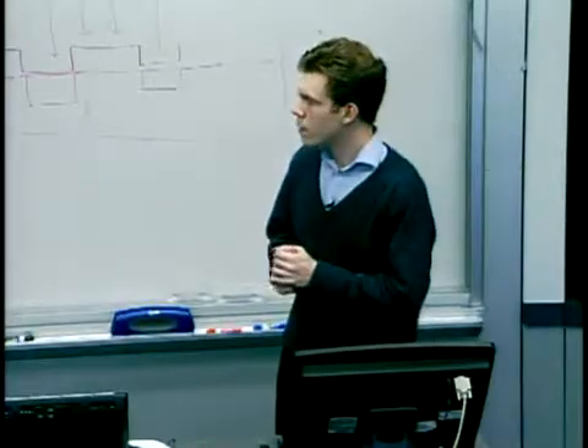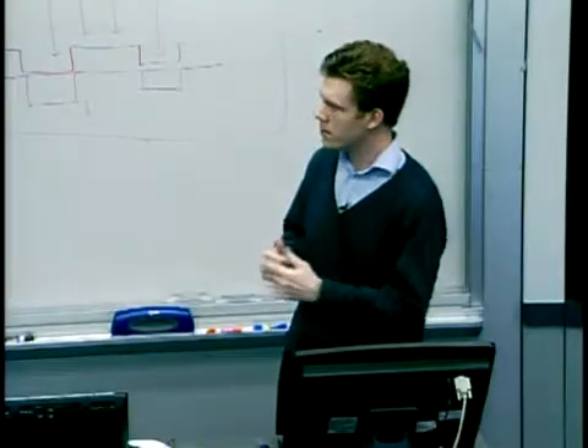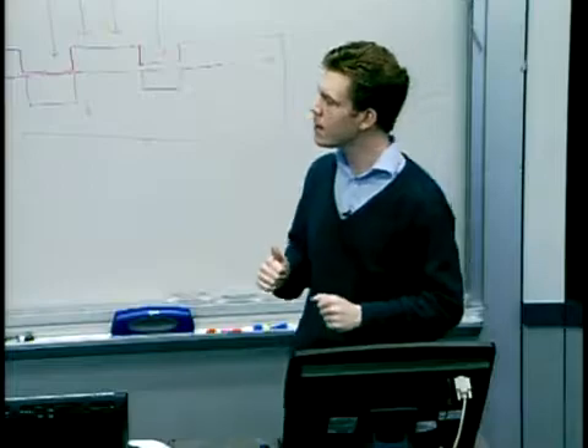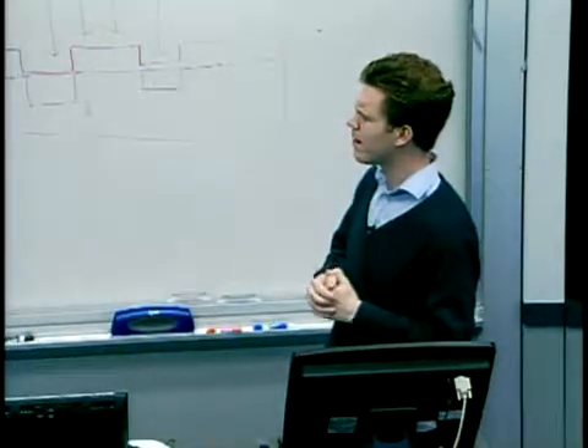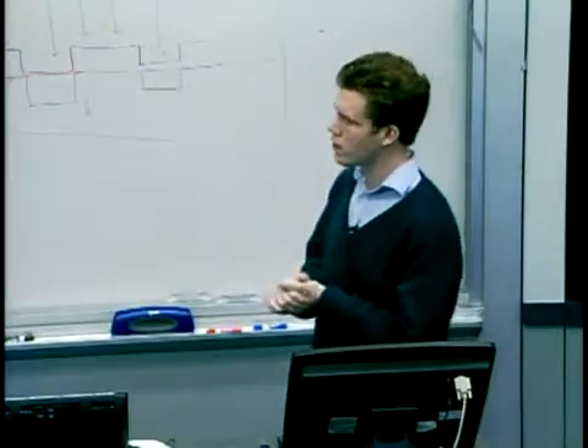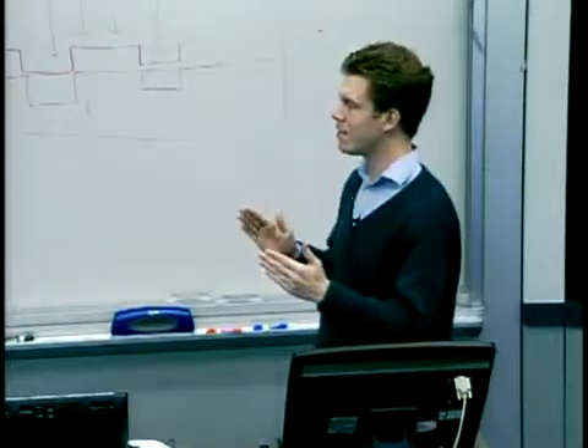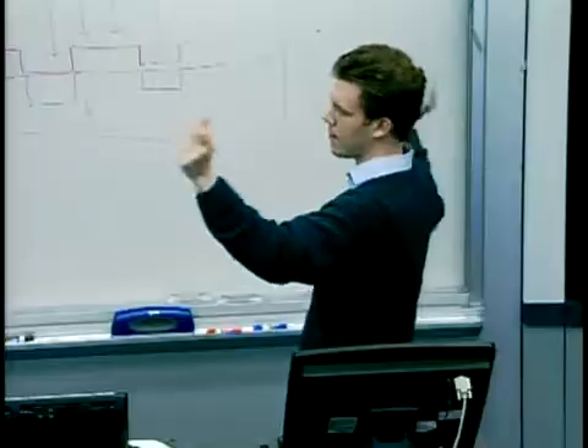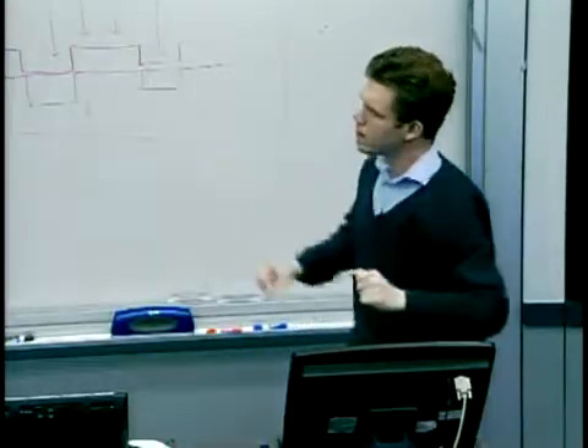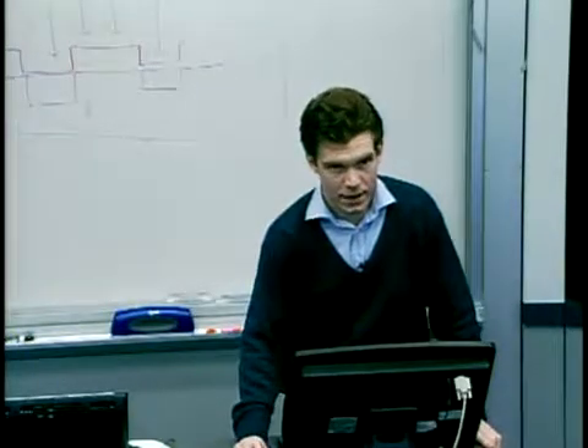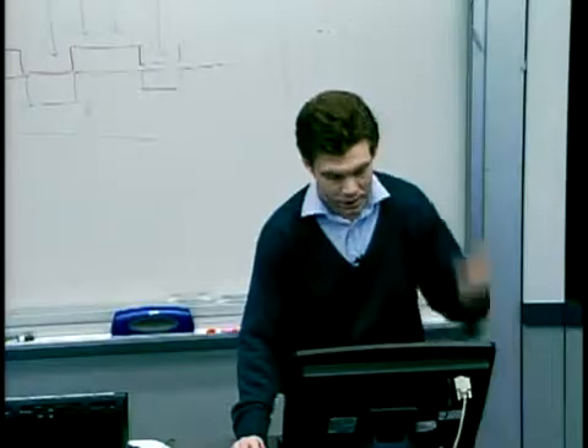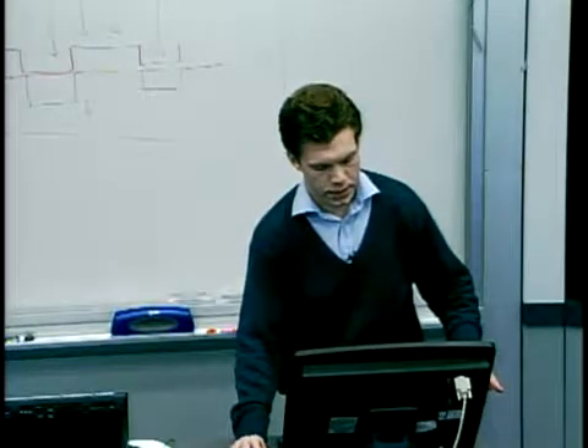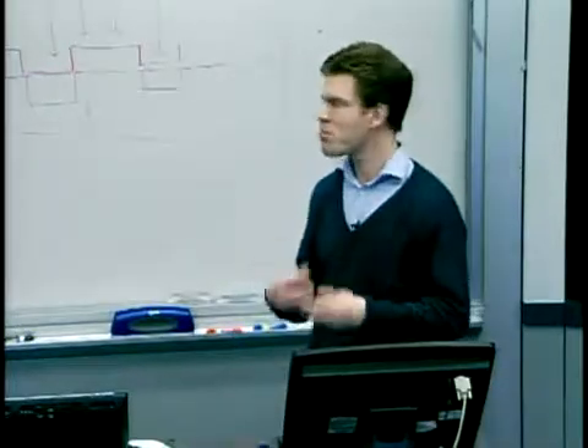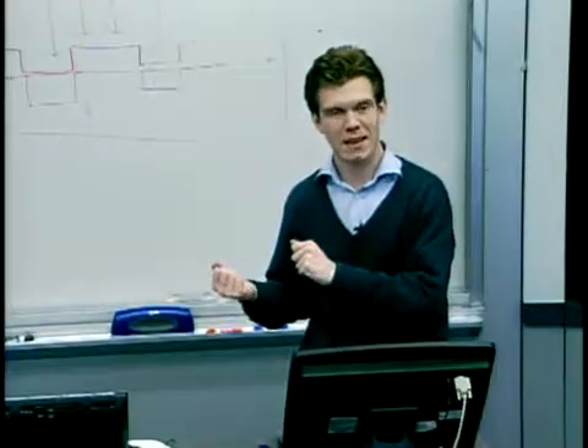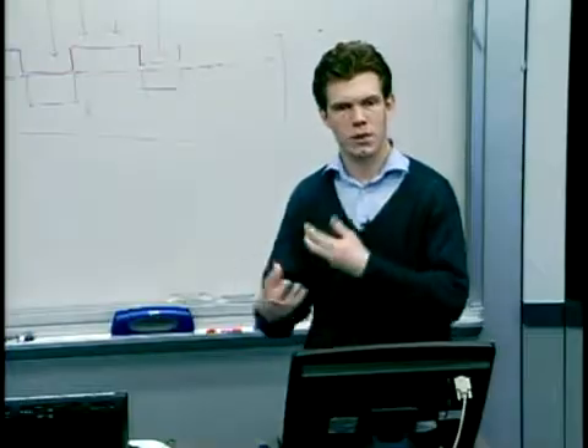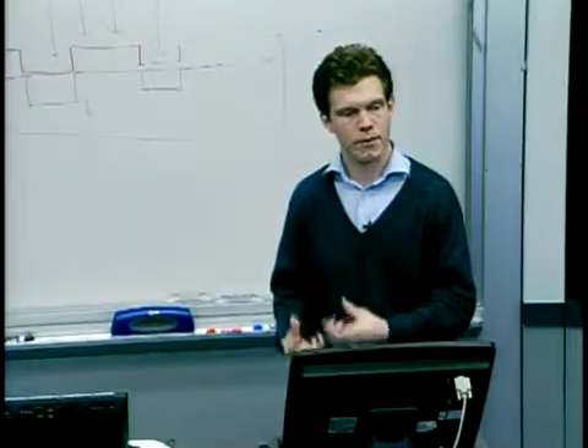So we tried this with some very simple geometries, lots of parallel channels that we had etched into silicon. They were about 20 microns deep, and on the order of 120 microns in pitch. There are many channels going across the screen. But what we show here is, on the left, scanning electron micrographs of cross-sections through those embossed structures where a variety of different loads have been applied. And the loads were held for less than a minute. So it's our working assumption here that all the deformation was to do with the rubbery behavior of the material, and there wasn't really enough time for plastic flow to occur.